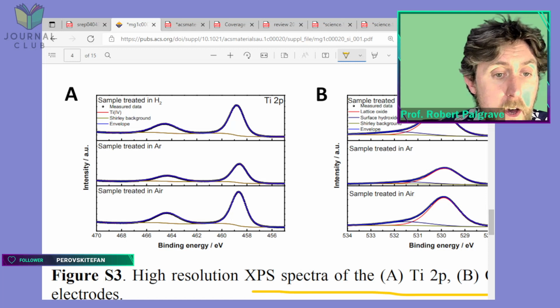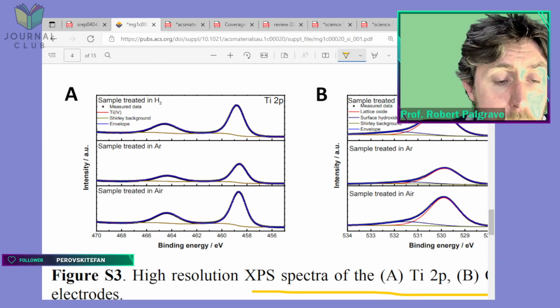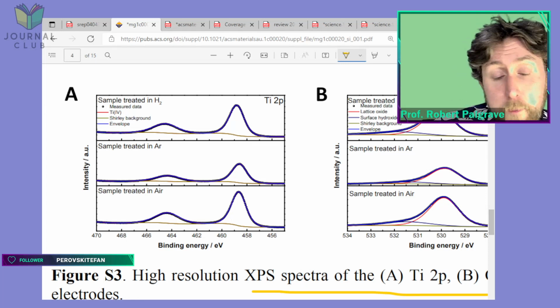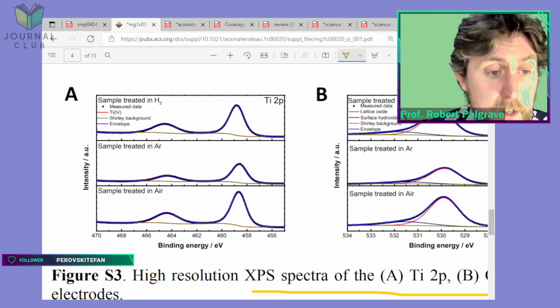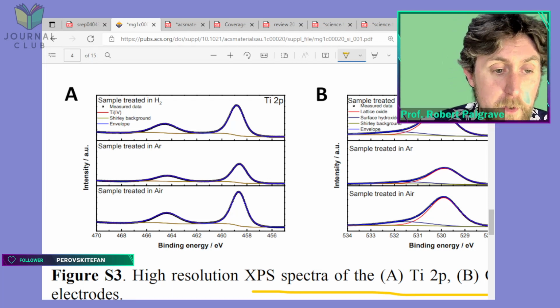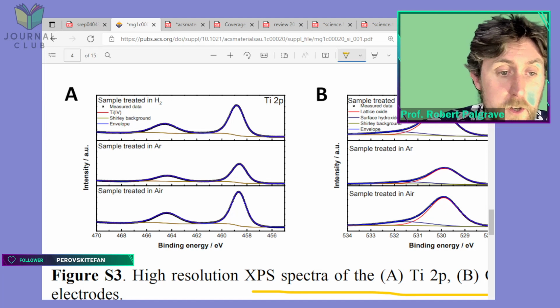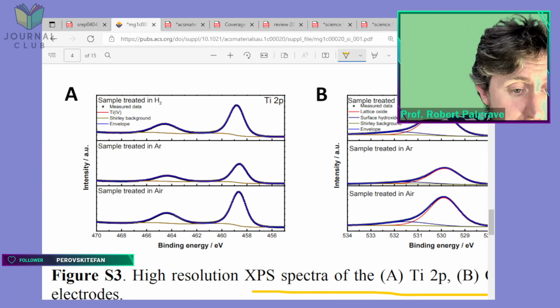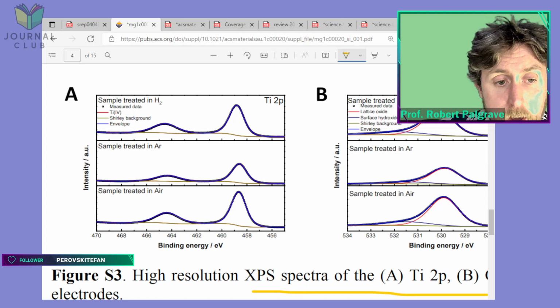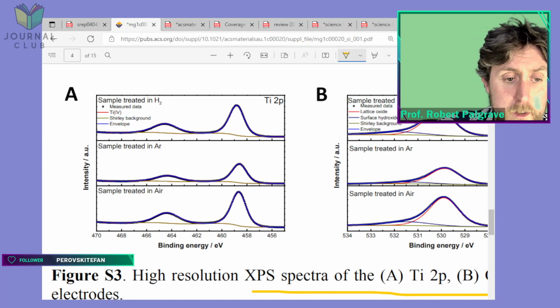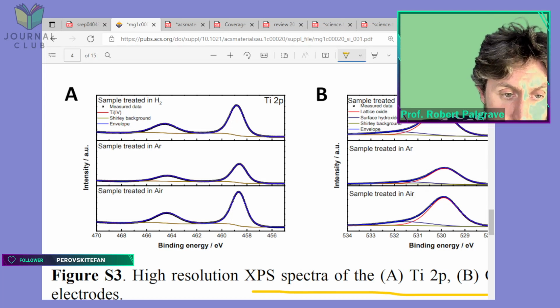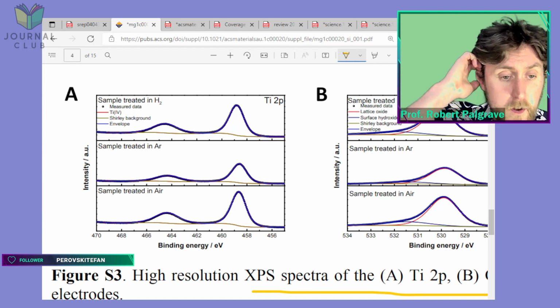So you have these two peaks. This is called a spin orbit doublet. You always expect this with titanium 2P because it's a p orbital, which has an angular momentum of its own, so it can couple with the spin of the electron to give these two peaks. So the spectra kind of look the same. I mean, this one's smaller. I don't know why, maybe they haven't normalized them. I don't think that's significant. I think there's a shift in the position of the peaks, which they'll talk about a little bit in the paper.